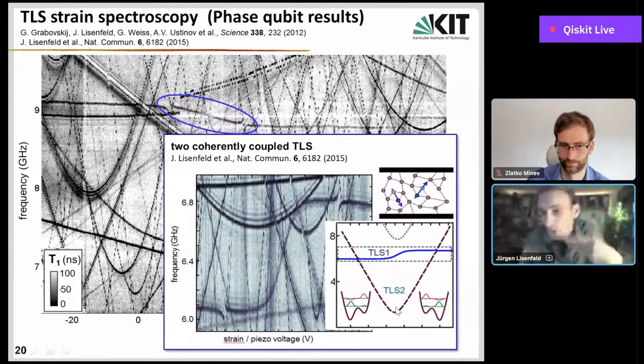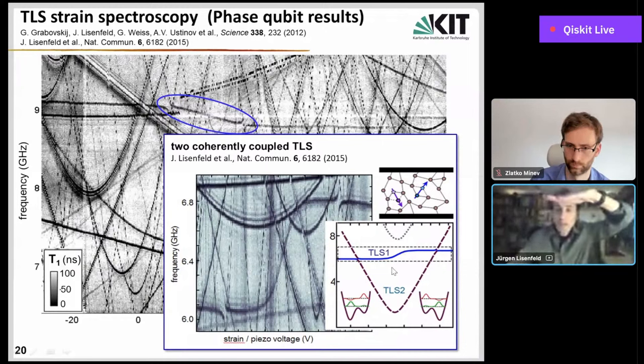So we basically flip this defect. And if you do this, we see that TLS1 responds with an adjustment of its energy splitting. So this is just a typical longitudinal coupling. You see that the energy of one defect depends on the state of the interacting defect. And this is just what we can directly see here by tuning this defect through the symmetry point.